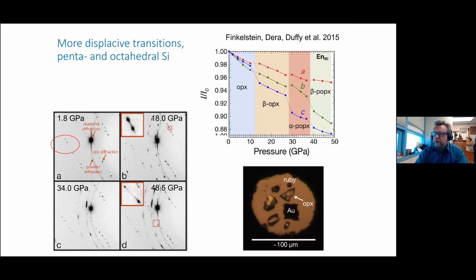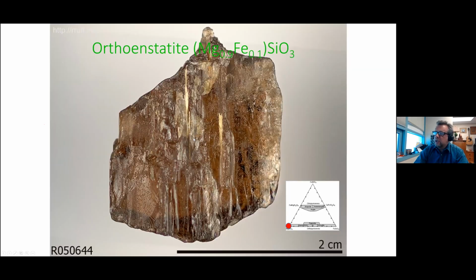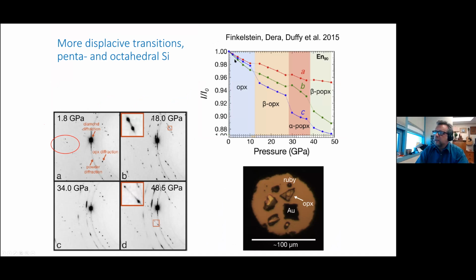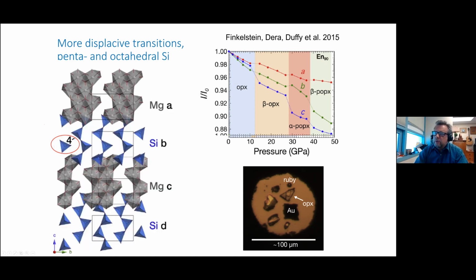We performed a lot of additional experiments afterwards, changing both the composition along the enstatite ferrosilite join, as well as extending the pressure range to much higher pressures. And we discovered that orthopyroxenes go through a series of several phase transitions. The one that we found with Jin and Jay was just the first one that happens just above 10 gigapascals and leads to a monoclinic orthopyroxene. We found two additional phase changes in enstatite 90 with 10% molar percent iron. And we found that these additional changes change symmetry again from monoclinic to orthorhombic and to another phase group in the orthorhombic system.